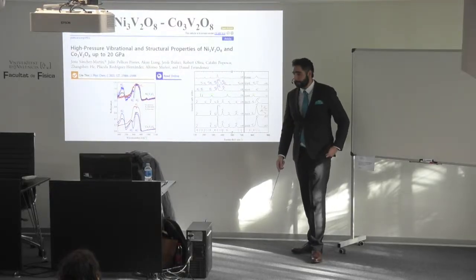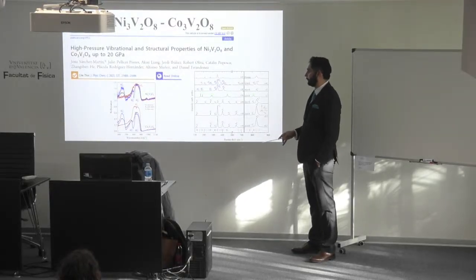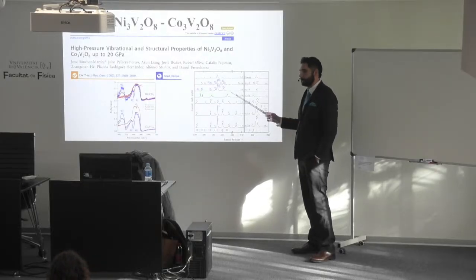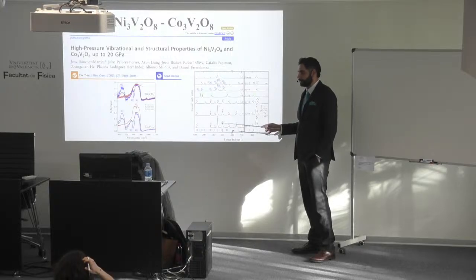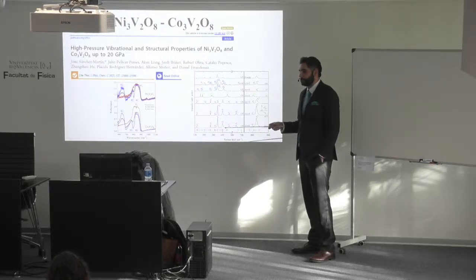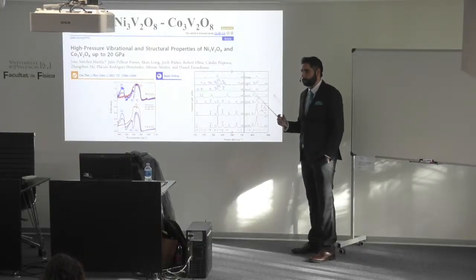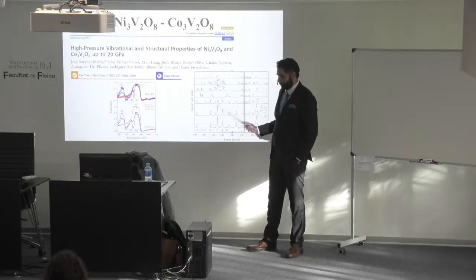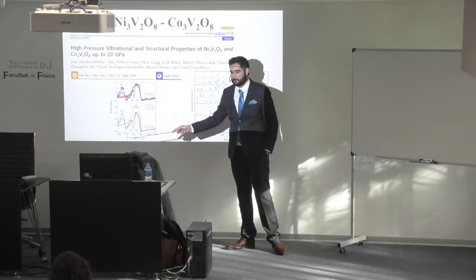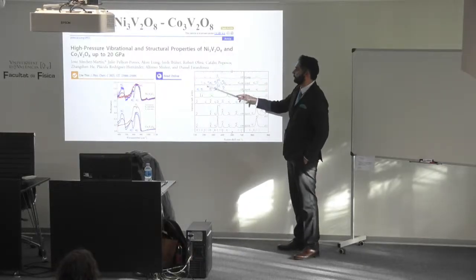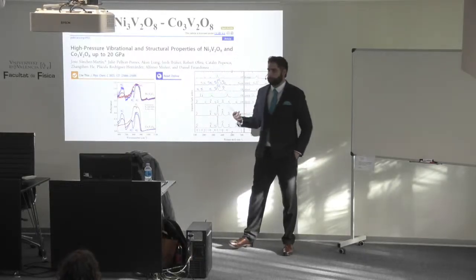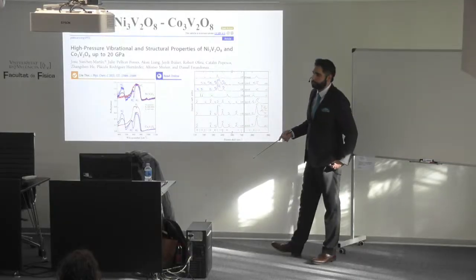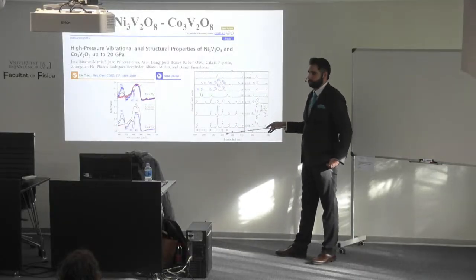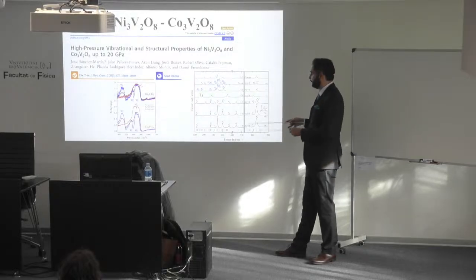For nickel and cobalt orthovanadates, they have the same structure, an orthorhombic one. And in this case, we focus more on the vibrational analysis because we have very large single crystals. So we had the opportunity to orient them. And this allows us to do Raman, polarized Raman, and also polarized infrared measurements. So in this case, those samples up to 20 GPa do not go through a phase transition, but their vibrational characteristics are reflected.